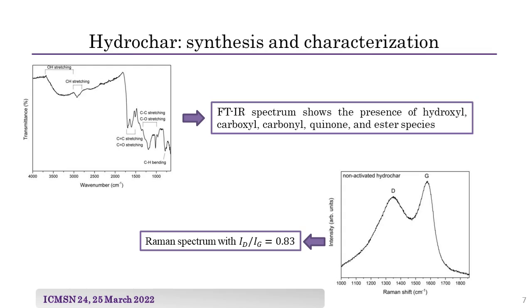The surface of the microspheres is covered by functionalities, as demonstrated by the infrared spectrum. Peaks can be interpreted as being due to the presence of hydroxyl, carboxyl, carbonyl, quinone, and ester species. The porosity of hydrochar microspheres was studied by nitrogen adsorption-desorption experiment, and before activation, the specific surface area was 12 square meters per gram.